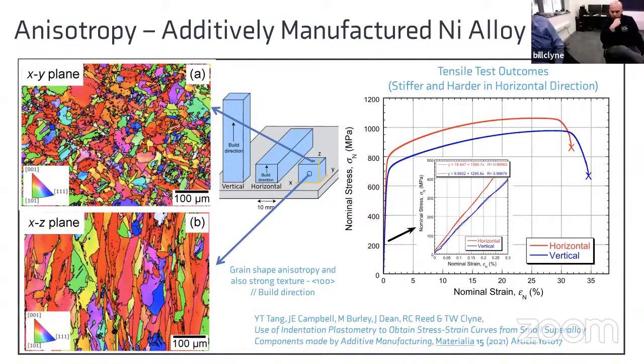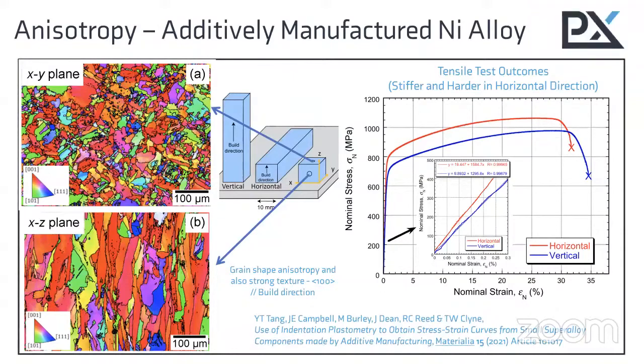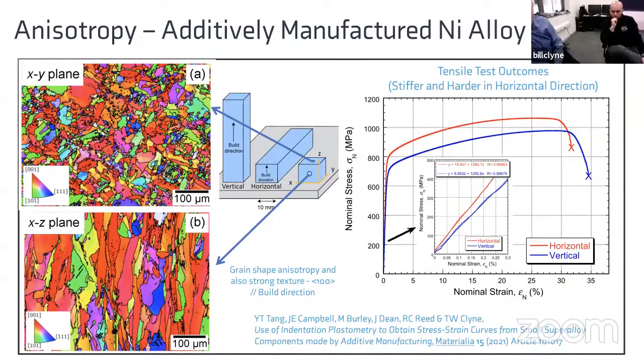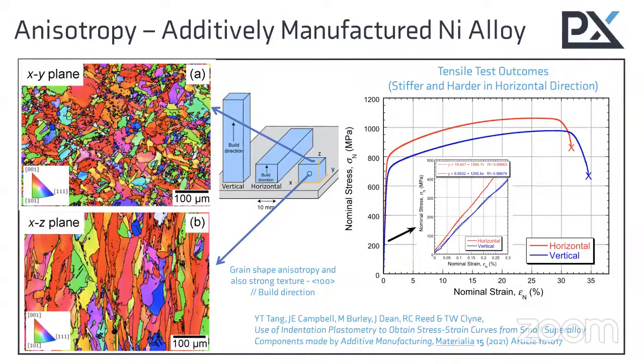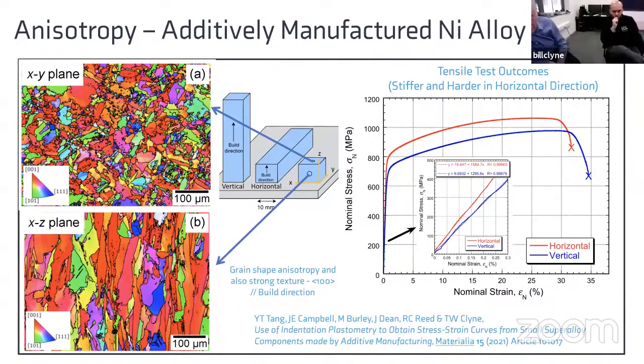What's happening here is that obviously assemblies of grains are deforming in a cooperative way. If there is no texture and the grains are equiaxed, then obviously you'd expect it to be isotropic, to deform in a similar way, no matter which direction you loaded it in. But if it is textured and if it has shape anisotropy, there will be some differences. And here you're clearly seeing that it's harder in transverse directions. So I suspect it's the texture that's the more important of the two.